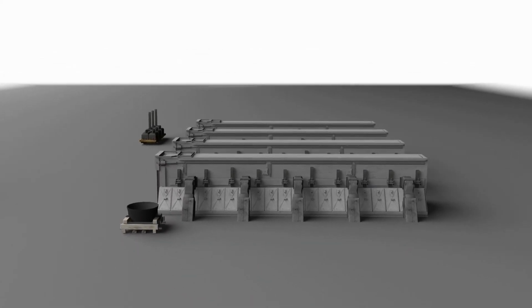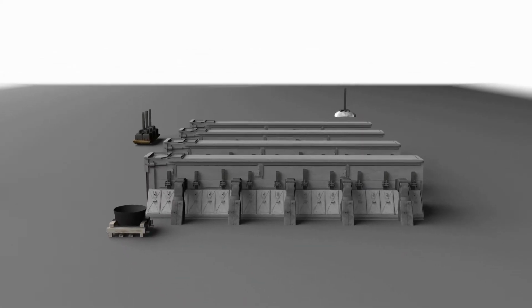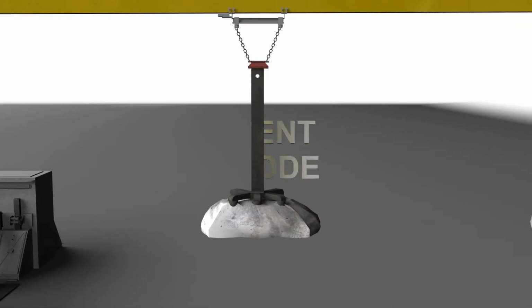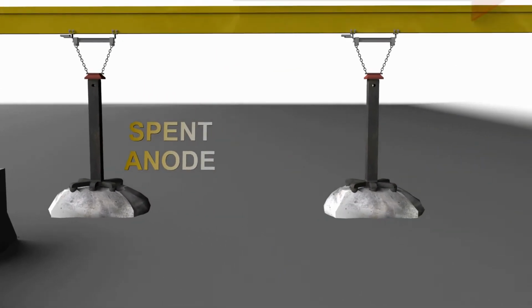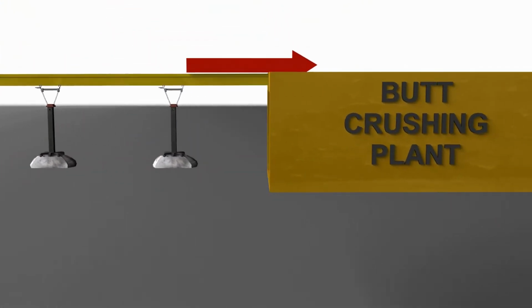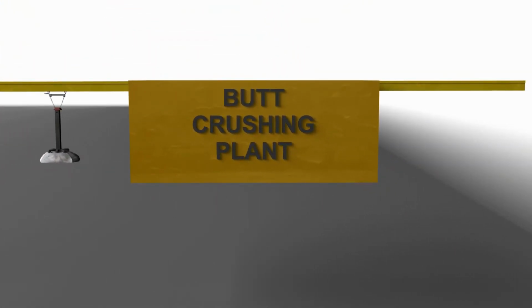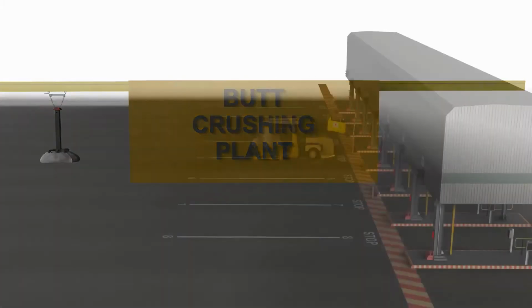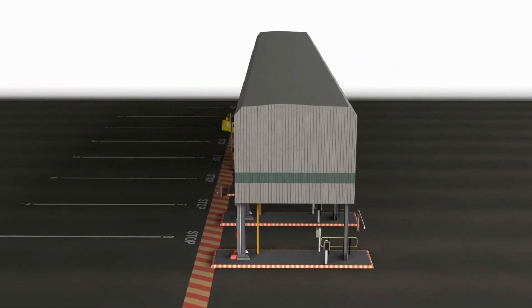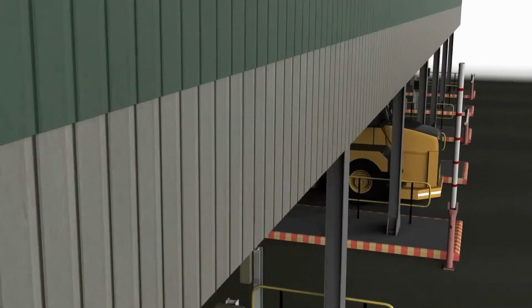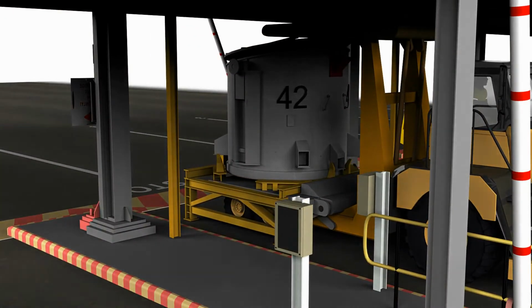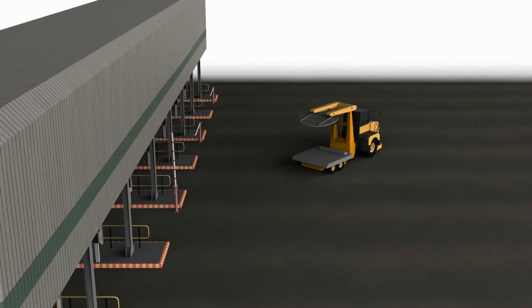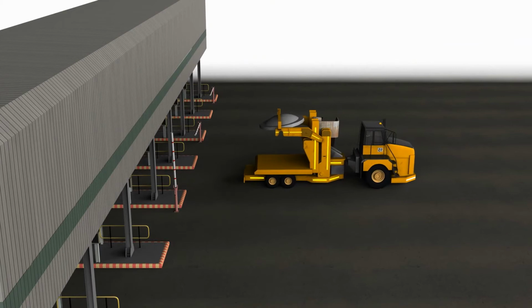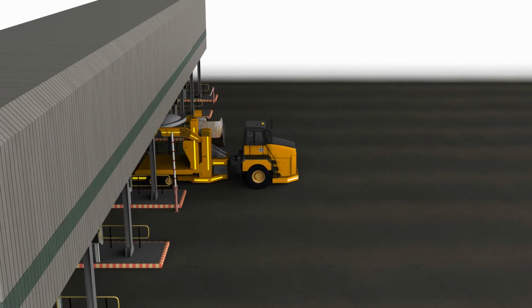The anodes are replaced every 27 days. The spent anodes, called butts, are taken to the butt crushing plant. Once crushed, the unused anode material is blended with coke in the paste plant for the manufacture of new anodes. Bath, cast iron, and anode stems are also recycled. The ladles containing molten aluminium are transported on ladle transport vehicles to a weighbridge where the ladles are weighed. The ladles are collected by ladle tilter transport vehicles and taken to the cast house.